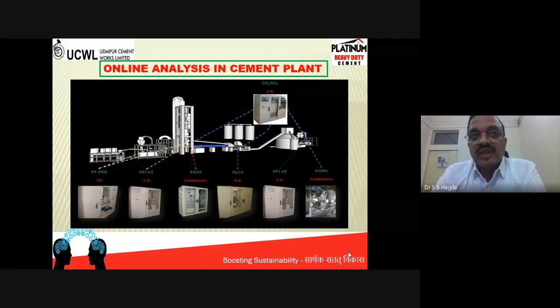There is also a theory in the cement chemistry that the 3 to 32 micron particle sizes are very vital for the generation of cement in the system. So if the 3 to 32 micron particle size is more than 60%, it is good. So 65% or 70%, whatever higher percentage is there, it is considered as very good in view of development of cement strength. So as per the technology and as per the online analysis, we can change the percentage.